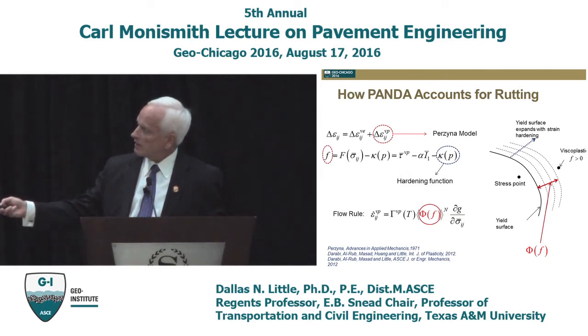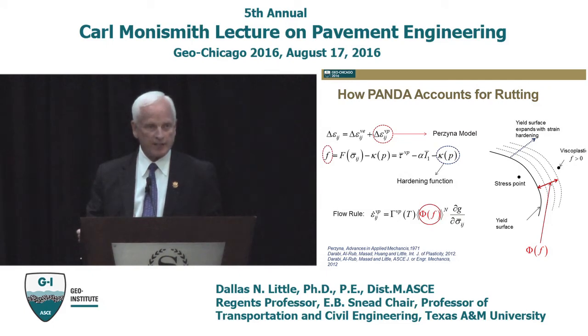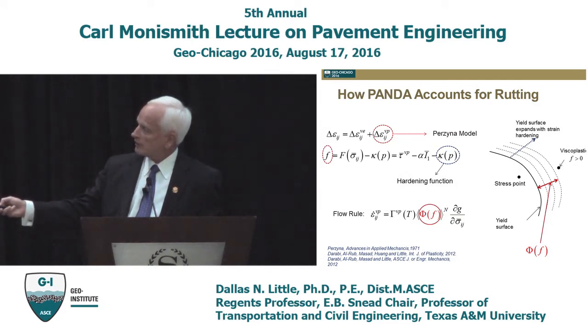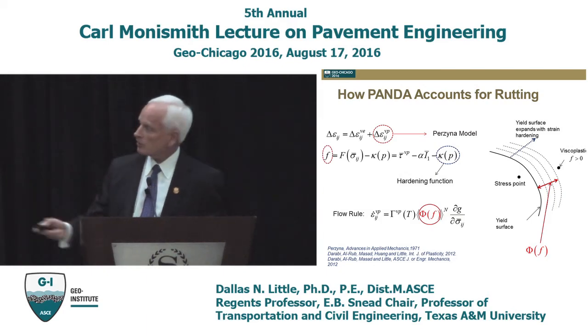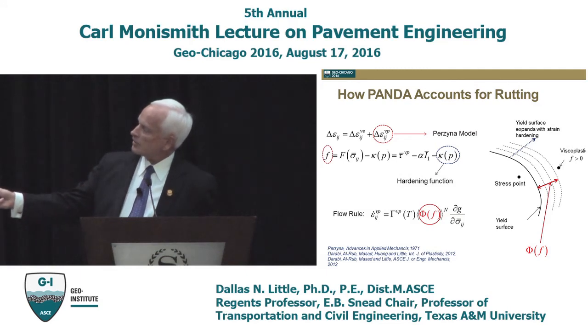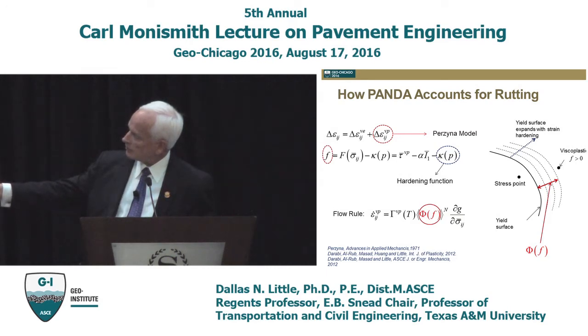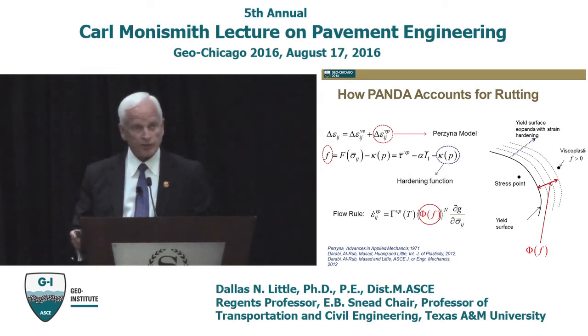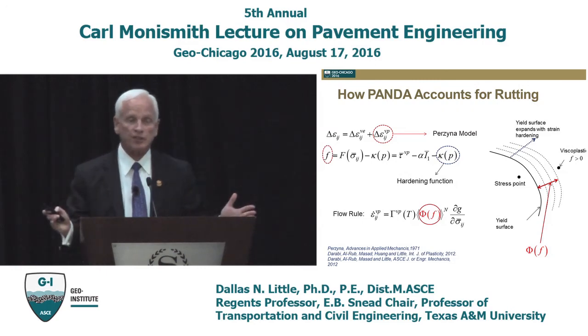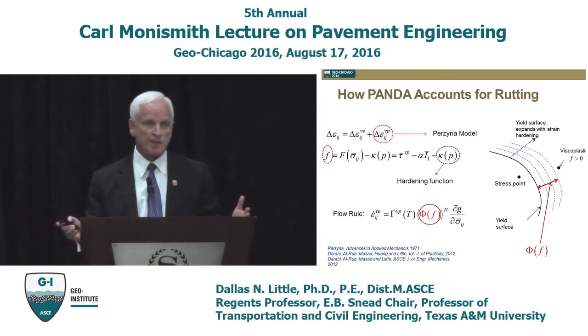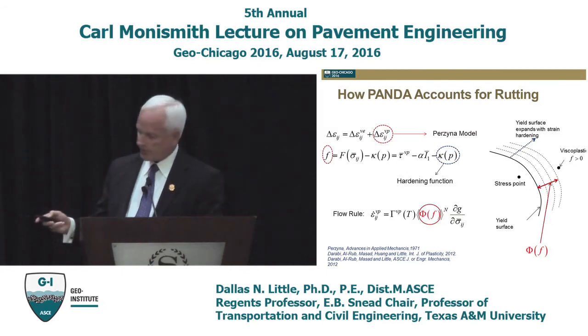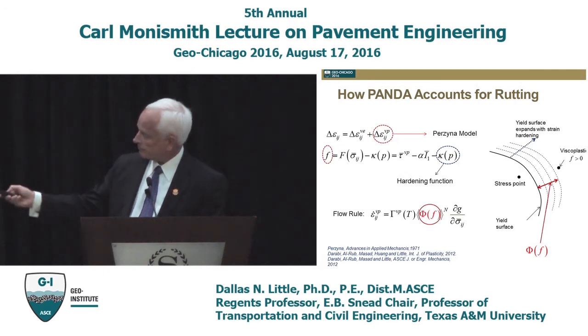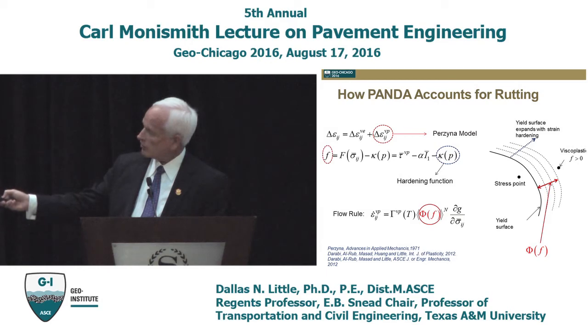And then within the brackets here that are called Macaulay brackets, there is a function, a different phi function of F, which is called an overstress function. And essentially what this term does, it identifies the stress point. If the stress point is behind the yield surface, and you can see the dark curve here, that's the yield surface. If it's within the yield surface, no plastic deformation occurs. It simply does not develop rutting. If it occurs outside that yield surface, then plastic deformation occurs.